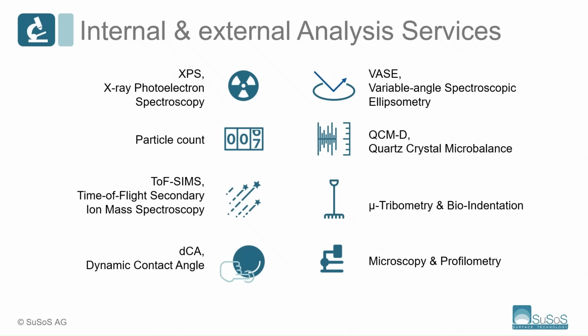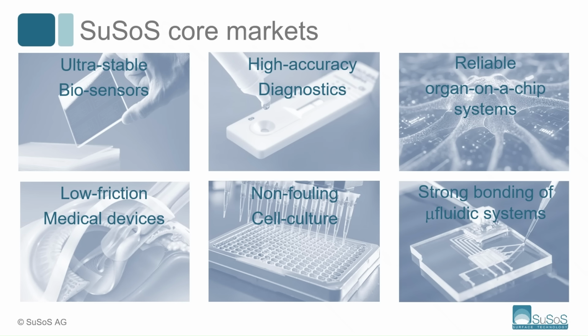We have X-ray photoelectron spectroscopy and time-of-flight secondary ion mass spectrometry to check the surface chemical characteristics. We have variable angle spectroscopic ellipsometry to assess the thickness of the coating. We have particle count, quartz crystal microbalance. We have microtribometry and nanoindentation for the physical and tribological properties of the materials, as well as dynamic contact angle for checking the hydrophilicity and hydrophobicity of the surfaces, and the various microscopes and profilometers. As you can see, the possibilities and the issues are limitless.